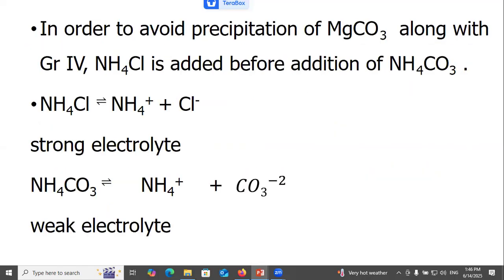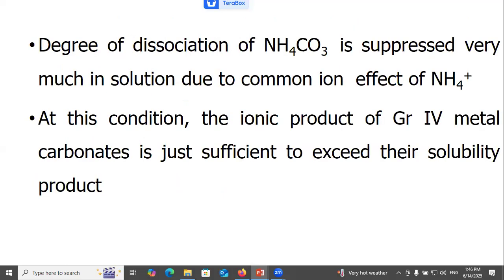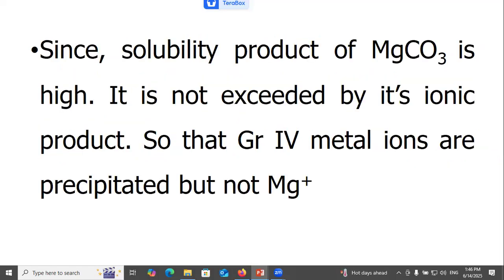In order to avoid the precipitation of magnesium carbonate along with group IV, ammonium chloride is added before the addition of ammonium carbonate. Ammonium chloride dissociates as ammonium plus chloride, a strong electrolyte, but ammonium carbonate is a weak electrolyte. The degree of dissociation of ammonium carbonate is suppressed very much in solution due to the common ion effect of ammonium. At this condition, the ionic product of group IV metal ion carbonates is just sufficient to exceed their solubility product. Since the solubility product of magnesium carbonate is high, it is not exceeded by its ionic product, so that group IV metal ions are precipitated but not magnesium.